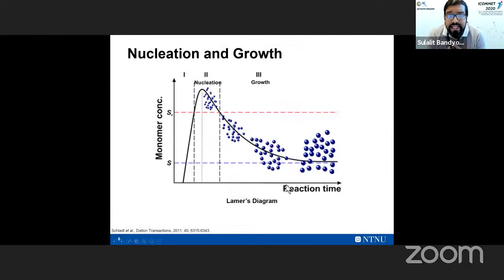We'll look into it in a bit more detail in the next slide through a classical mechanism called the LaMer diagram. What it basically talks about is that S here represents supersaturation. There is a critical supersaturation required for nucleation to happen. If you follow this curve, follow my cursor on the screen, as the concentration goes higher up, S is the solubility limit, and the system starts to become supersaturated. But from S until Sc, there is no nucleation happening because although the system is supersaturated, it requires an additional kick to form the first nuclei, which can be derived from classical nucleation growth theory.